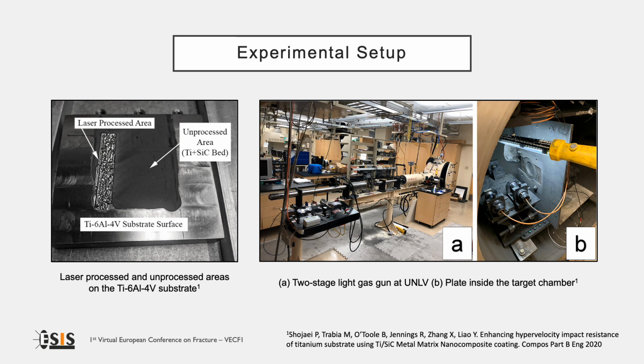The experimental apparatus in the University of Nevada, Las Vegas is shown in the figure on the right. Hypervelocity impact test was performed using a two-stage light gas gun. The projectile was a Lexan cylinder with a diameter of 5.5 mm, a length of 8.6 mm, and a weight of 0.25 grams. The impact velocity varied in the range between 3.7 to 5.4 km per second.